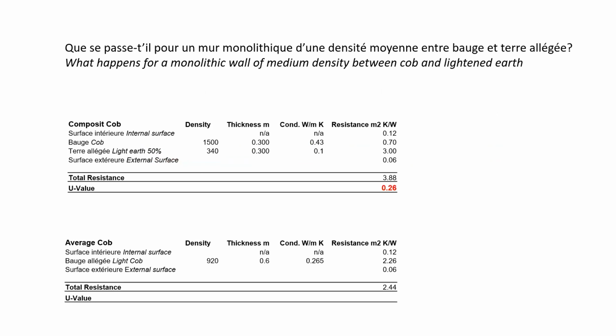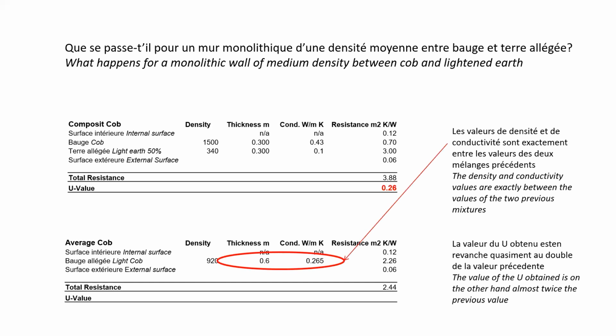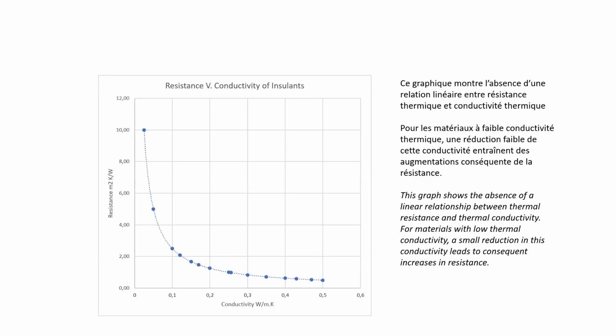We also wondered what would happen with a monolithic wall of a medium density between the cob and light earth that we mentioned. So if we had a light cob to get an average density of 900 kilograms, we realized that with the same thickness of 60 centimeters, the U value was much higher, at 0.41, and this means we weren't complying with thermal regulations, especially in England, and this would have meant that it was also harder to use in France. So this graph here shows you the relationship between thermal resistance and thermal conductivity. It's not a linear relationship.